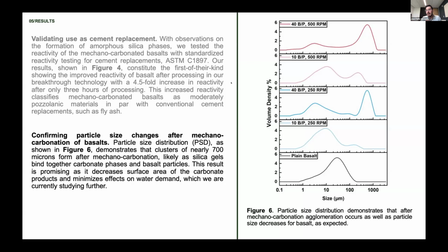Interestingly enough, when we're looking at that 10 ball to powder ratio, in both cases of 500 RPM or 250 RPM, we see that agglomeration still occurs, but the agglomerates are not as big as when we have that high ball to powder ratio.